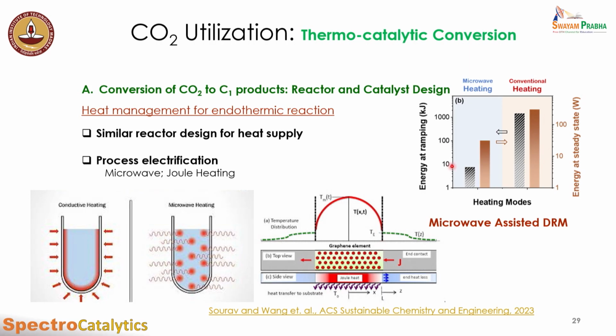Here is an example of how microwave heating versus conventional heating changes the energy input for dry reforming of methane, which is a highly endothermic reaction. When we ramp up the reactor temperature to the desired level, from room temperature to 900 degrees Celsius, and maintain the catalyst bed at 900 degrees Celsius, for the same amount of methane conversion in both cases, we can see the heat required by microwave heating is at least 10 to 100 times lower compared to conventional heating.